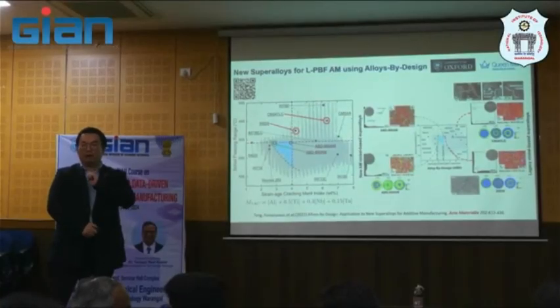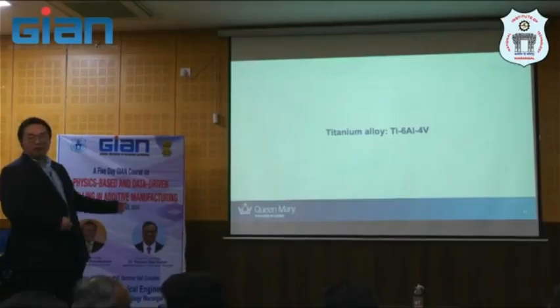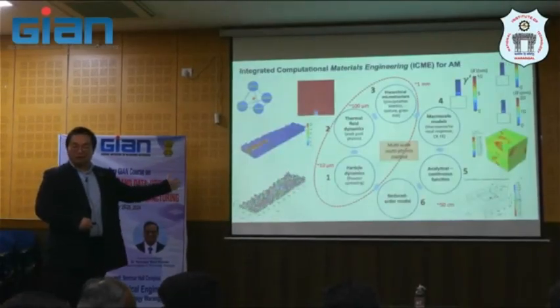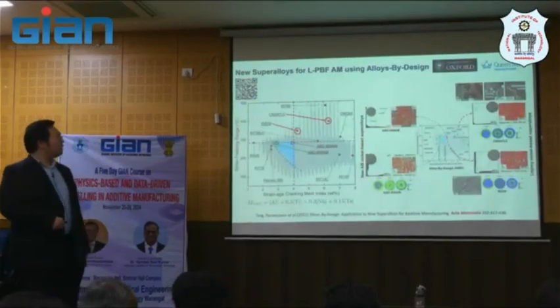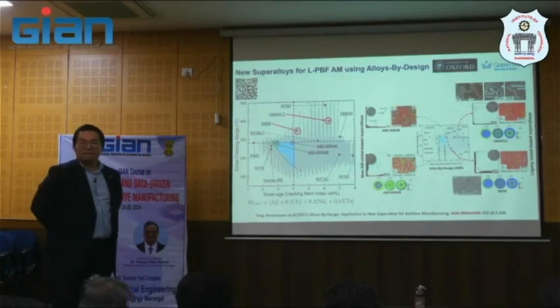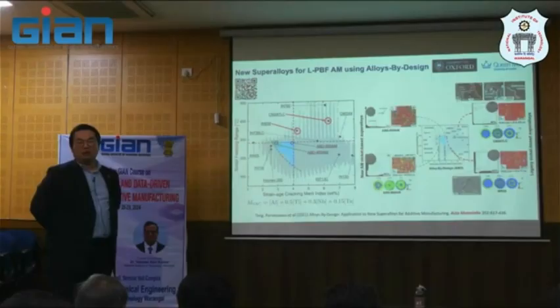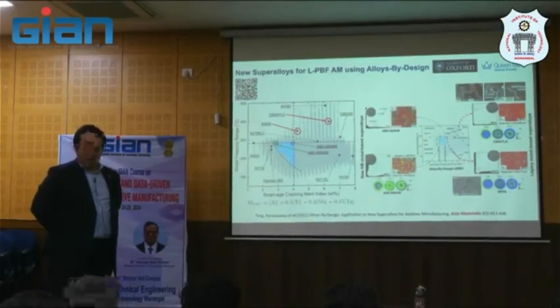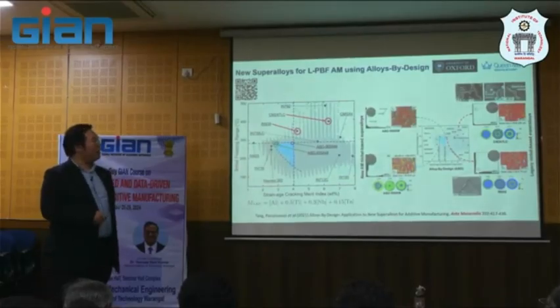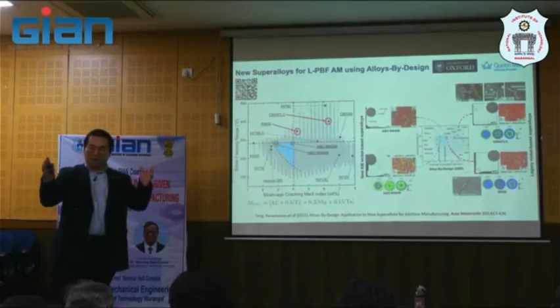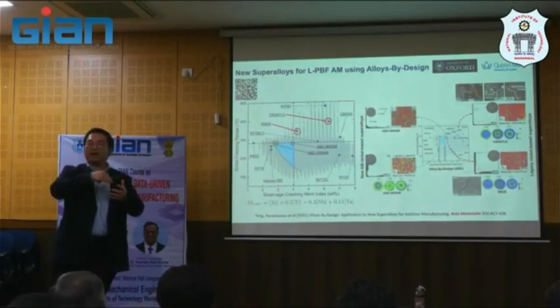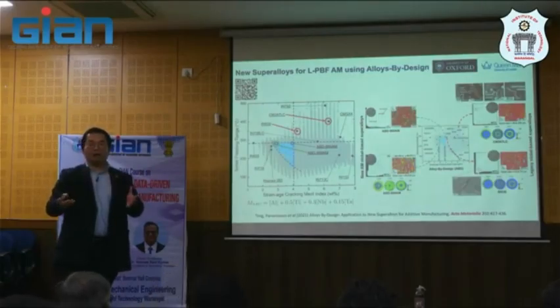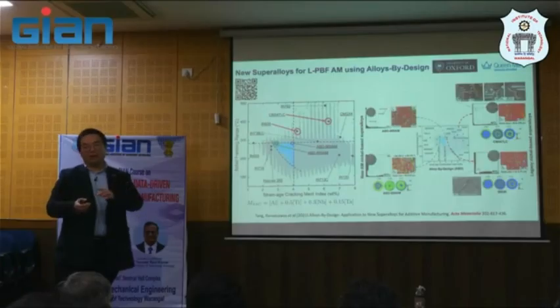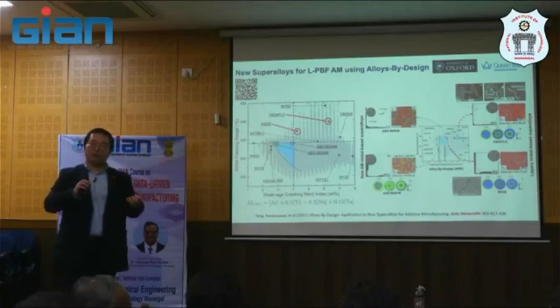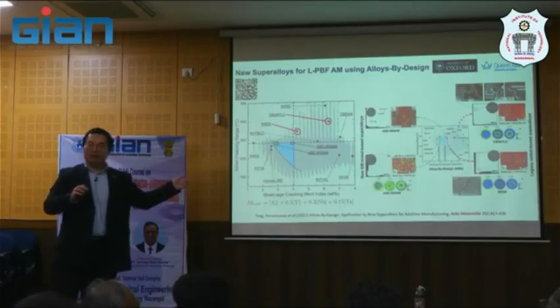No, be careful. I already said there are so many crack mechanisms actually acting on this. You can see more in this Acta paper about how many crack mechanisms operated. But what is your question? So in the micrographs, they are solidification cracking? It will be a mixture: ductility dip, liquation, lack of fusion. The crack here is hard to identify because based on imaging, the crack in this sense means any line in the microstructure. We have not classified yet because this is image-based analysis. It's not like tomography, where we can identify the features like in the previous work. That makes sense.